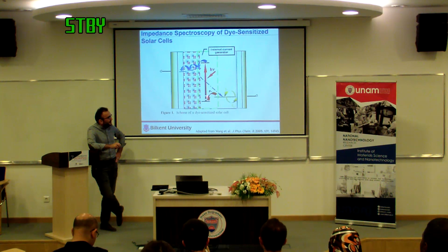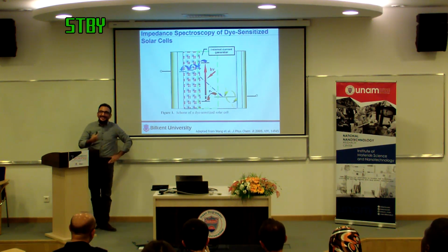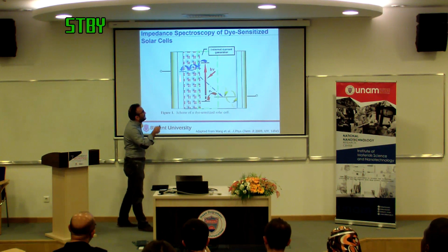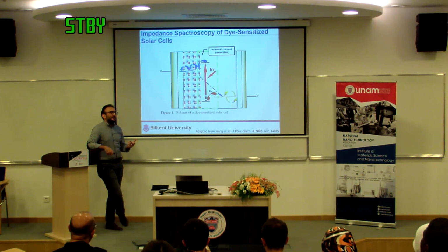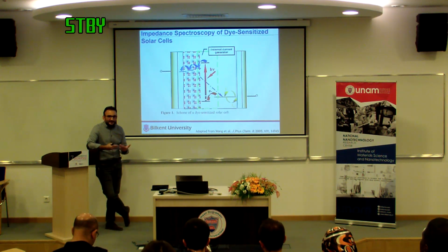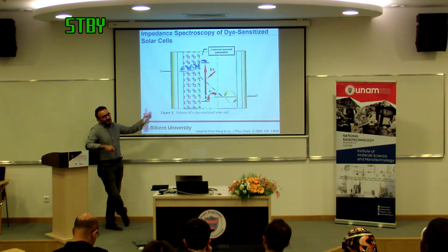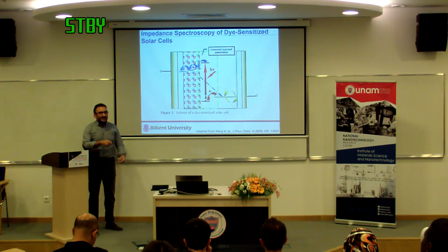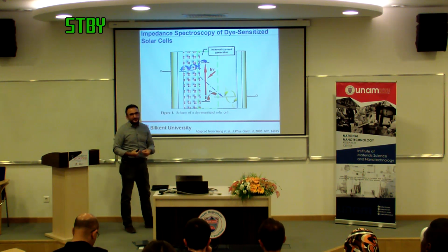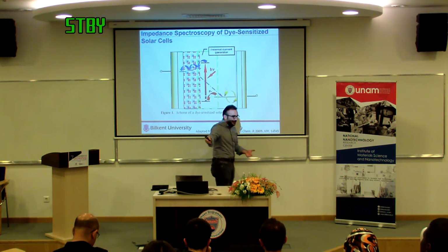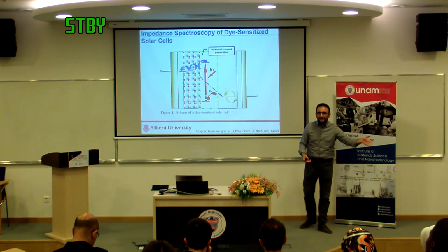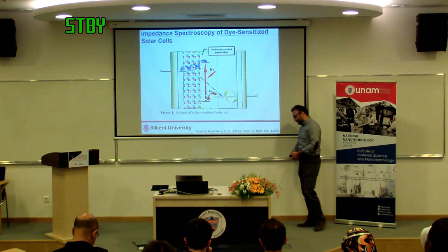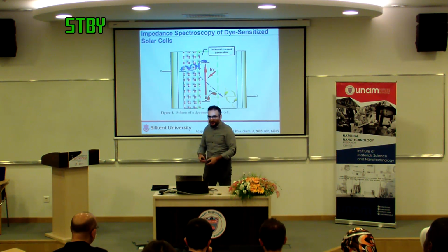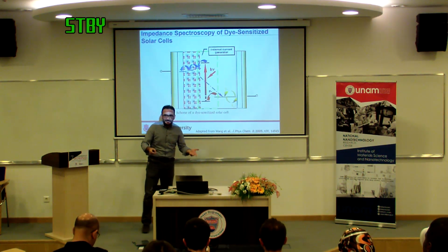And on the other side, you have some redox couple, generally iodide, triiodide, that does the other part of the reaction and completes the circuit. The advantage of this type of solar cell is because you have a dye molecule, you can tune the absorbance. In semiconductor solar cells, you're bound by the band gap. You cannot absorb anything lower than the band gap because your material doesn't absorb there. By using the dye here, you can do chemistry to tune what part of the spectrum this absorbs, and you can actually make dye-sensitized solar cells work even on cloudy days, because they can work with the green and the red part of the spectrum in addition to the UV and the violet. So these are probably not that useful in Central Africa, but they are pretty useful in places like Arnhem, where you don't have any non-cloudy days.